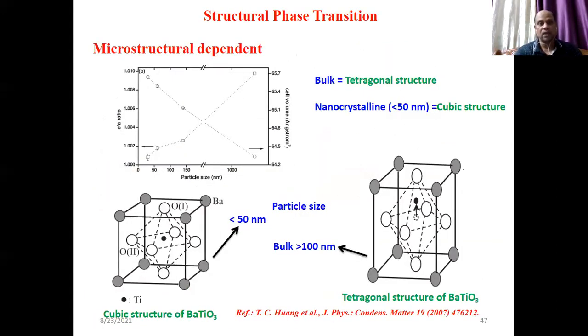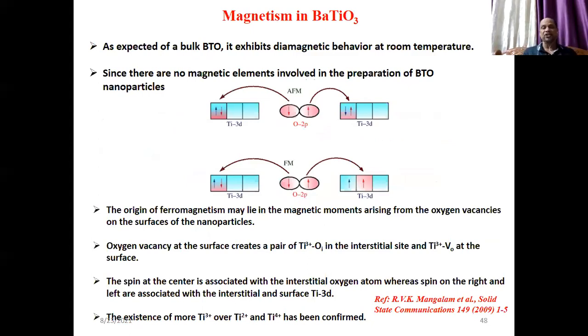This magnetism is due to the uncompensated spin at the surface, basically the superexchange interaction between titanium and titanium via oxygen, uncompensated spin. Okay, very interesting. At the surface, they are in the polaronic state, so you will get free electrons. It is not a bound electron. Don't confuse that. Titanium will have the d0 electron, but due to the polaronic effect at the surface, they will have spin momentum.